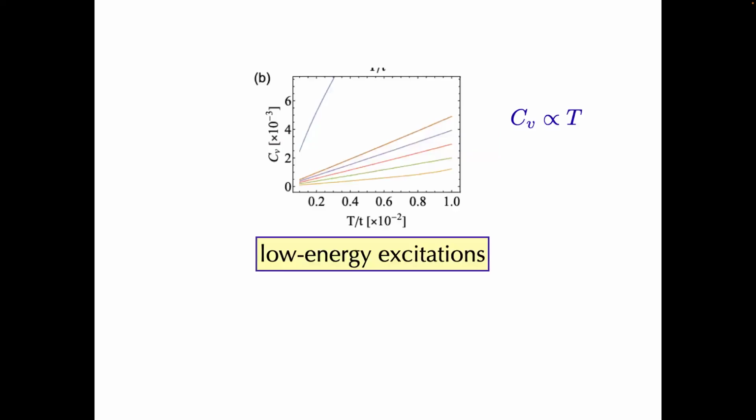Okay, now, is everything gapped? We know that the spin sector should have gapless excitation, at least that's what the case is in 1D. So we computed the heat capacity, and the heat capacity doesn't exhibit an exponential form. It's basically algebraic in the temperature at low temperatures, which means there are low energy excitations. These can't be charge excitations, these are spin excitations.